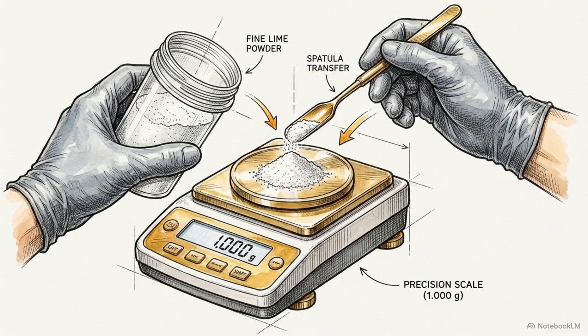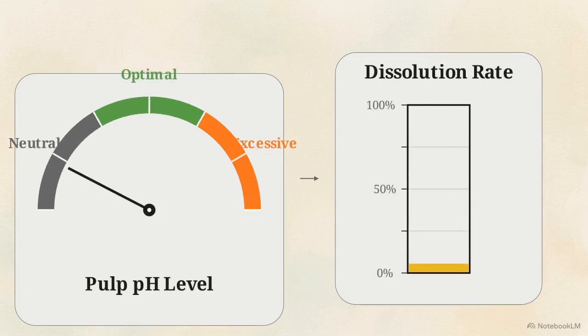That brings us to Phase 2, leaching parameters. We begin right away with Test 3, protective alkali dosage, typically using lime. This dial tracks the pulp's pH. Maintaining this specific alkaline range protects the cyanide's stability and reduces chemical loss. But watch the dissolution metric. Pushing alkalinity too high constricts the gold dissolution rate, slowing recovery.